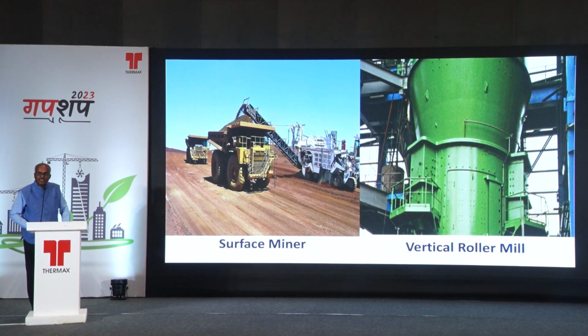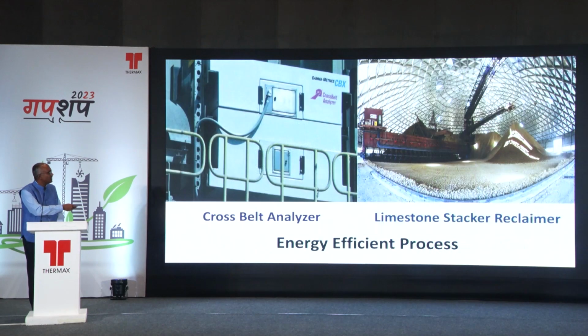Mining can be done through environmentally friendly means rather than only following drilling and blasting. You can go in for surface miners, which are more environmentally friendly. Vertical roller mill, wherein again particle size distribution of cement plays a major critical role, because it is not the fineness per se alone. In our test certificate, we would just be writing the Blaine's fineness test, but more than that, the particle size distribution is very important so that you get an economical mix design and a durable concrete can be made.